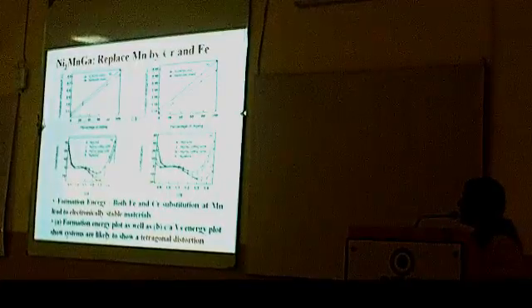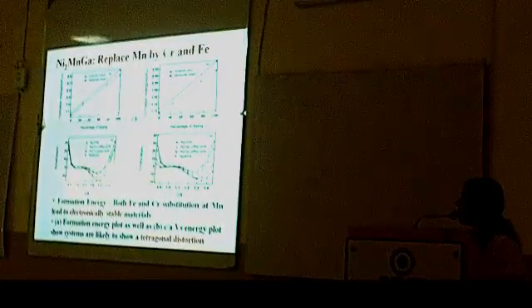This is the reference energy, and then the martensite phase, which has a C by A tetragonal distortion, so C by A not equal to 1. There is a minima here, showing that throughout the substitution it is prone to a tetragonal distortion.